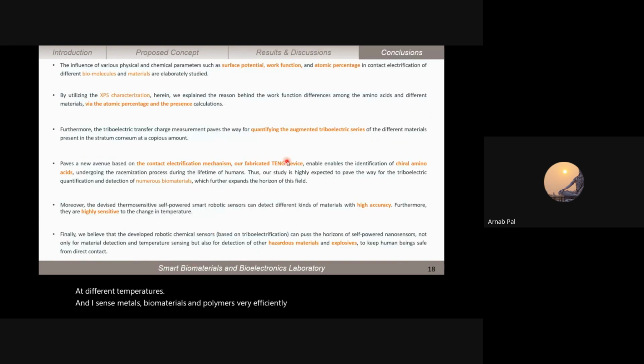So my conclusion is that in my whole work, I can explain the surface potential, work function, and atomic percent on different materials and biomaterials and their contact electrification process. I explain them via XPS characterization and their atomic percentage, quantifying and augmenting the triboelectric series of different materials, which can help other people to choose their materials during device sensing, device fabrication or something like that.